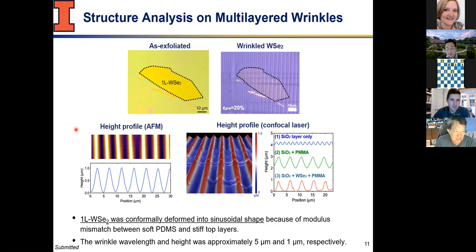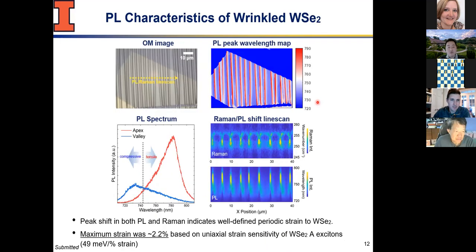But if you find a region there, you see these high profile wrinkles are fairly consistent, uniform. And you can do this using different techniques to measure the height and the wavelengths, for example, of the wrinkle that we have created with tungsten selenide. And the length scale, just to be clear, is that from one peak to the other peak is about 5 micron. And the height of the wrinkle is 1 micron. And we chose this dimension because we wanted this to be compatible with some of the optical techniques I'm going to use to probe this. And it has to be above the diffraction limit. So that's why it's a little bigger, but things can be controlled.